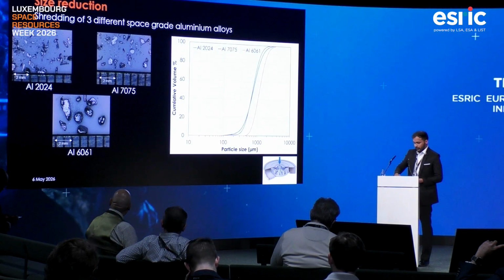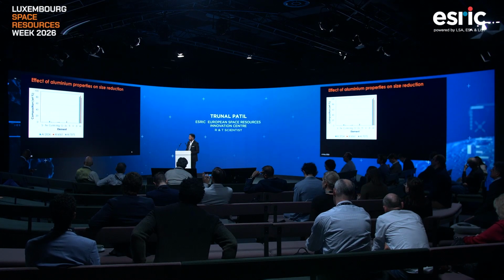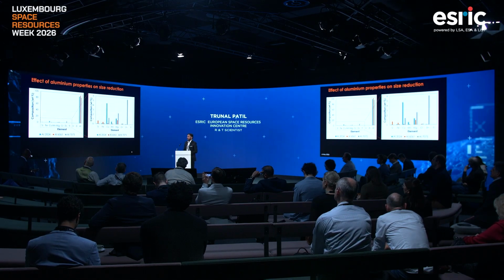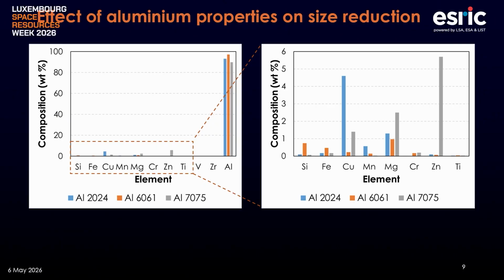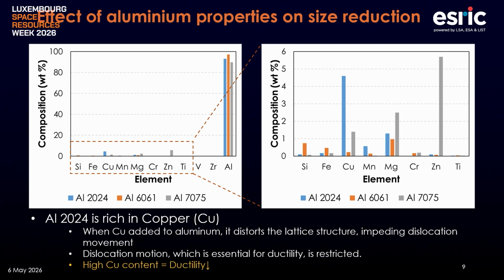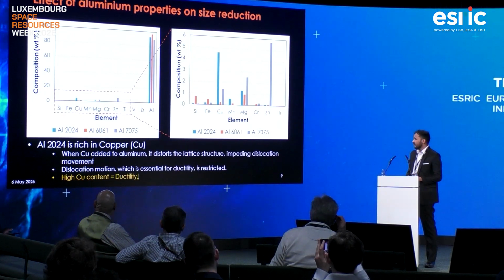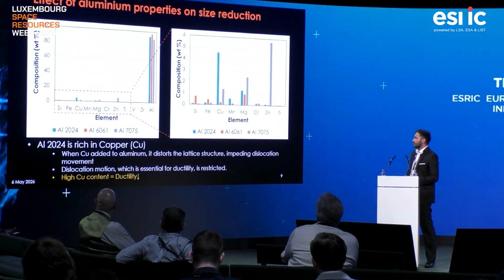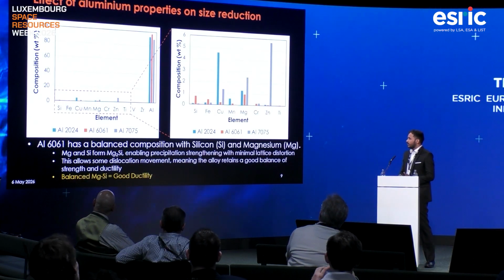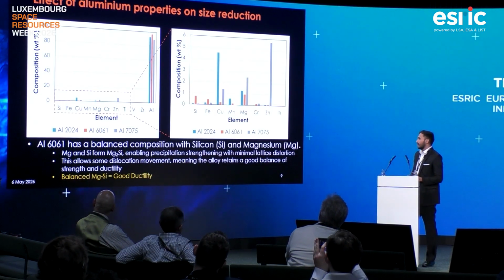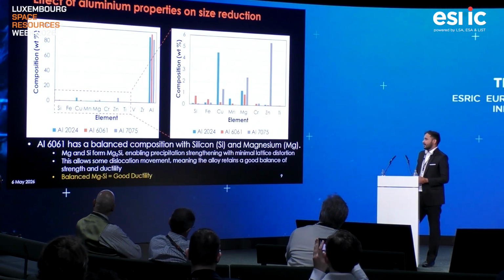So we wanted to see why this is happening in the aluminum particles. We further examined this effect with a composition analysis, and what we found is that there is a composition variation in these aluminum space-grade alloys. Aluminum 2024 is rich in copper, so this material is less ductile compared to aluminum 6061. Aluminum 6061 has a balanced composition with magnesium and silicon, so it has good ductility.